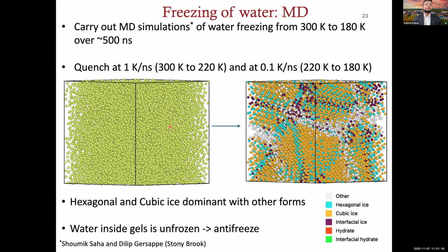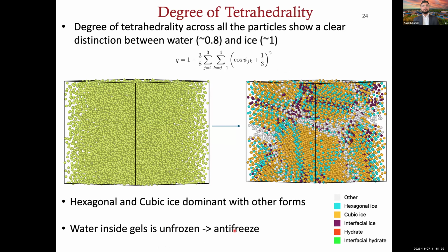And so that's why this is what we get, which is also seen in the literature when we try to simulate something like this. Now, one thing that was very interesting for us was that water inside the gels that I had shown earlier did not freeze. So that's a really powerful indicator that having a hydrophilic interaction like what we showed for the gels allows us to have this antifreeze behavior, right?